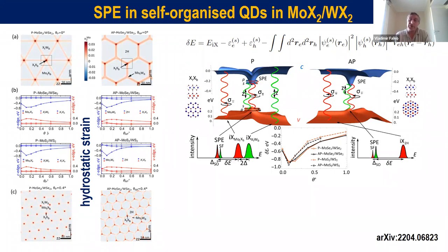And this large shift with respect to the known exciton energies places the resulting transition in the telecommunications range of photon activity, which may be quite a nice thing to use in terms of applications, because then we would get single photon emitters from those quantum dots exactly in the telecom range. So this is what excited us.